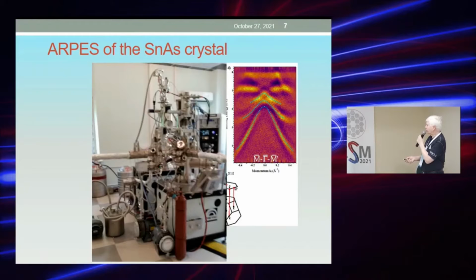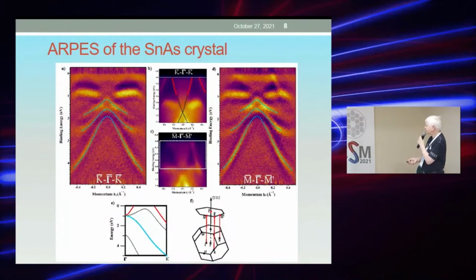Now the measurements were done. First, the band structure was measured with the ARPES machine in the laboratory, and then in St. Petersburg and in Moscow. The band structure is rather simple. It is nicely consistent with the calculated band structure. It consists of electron bands and hole bands in the gamma point.